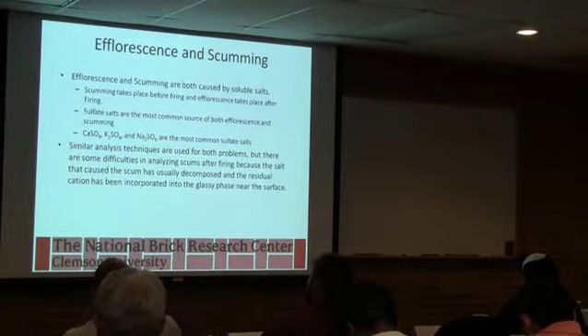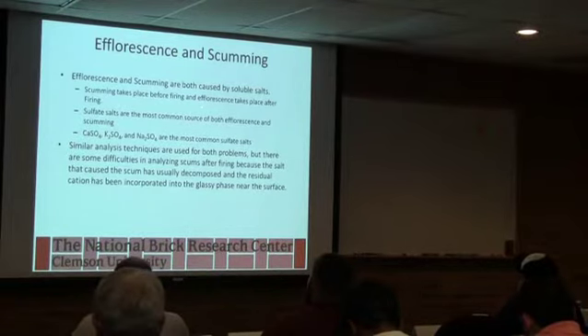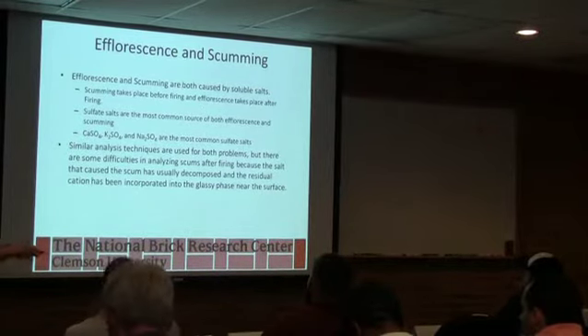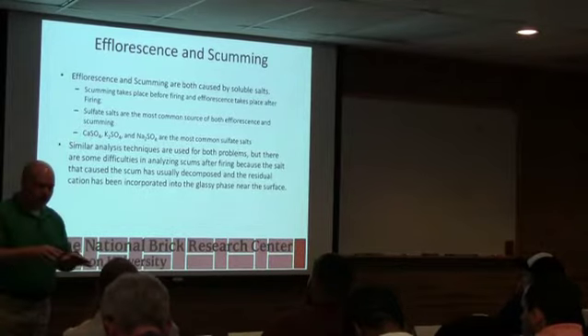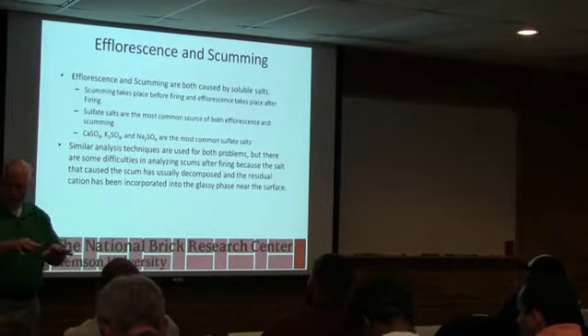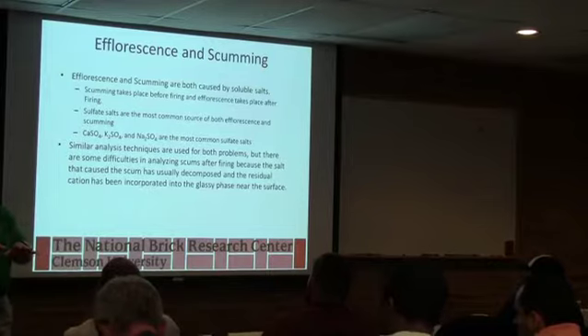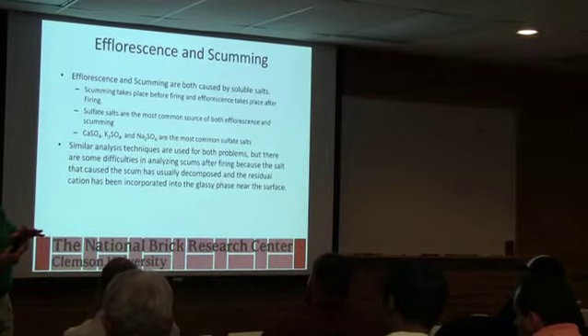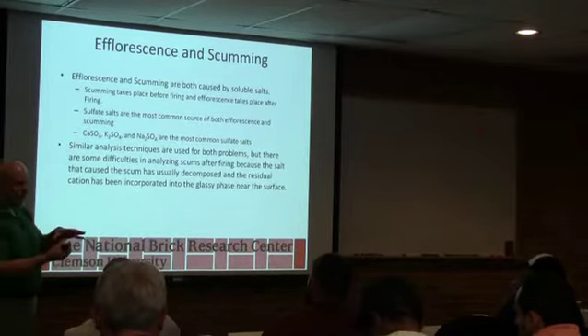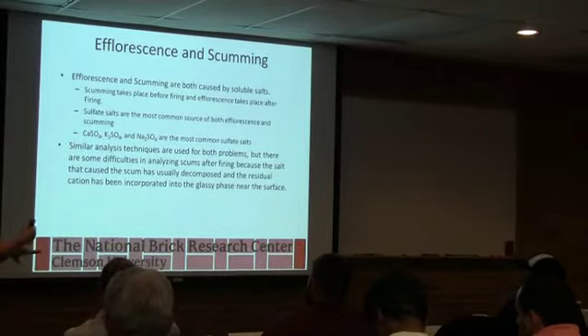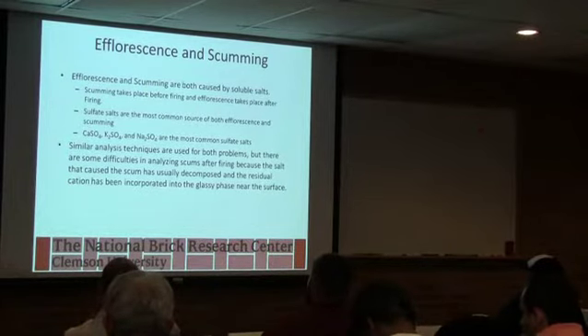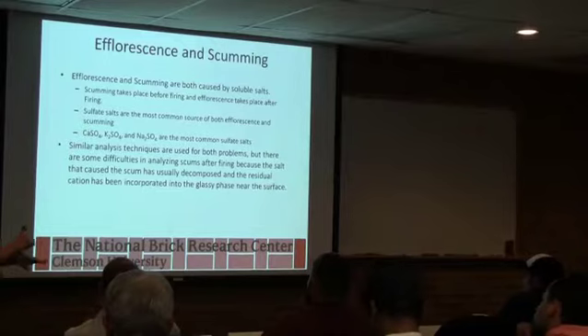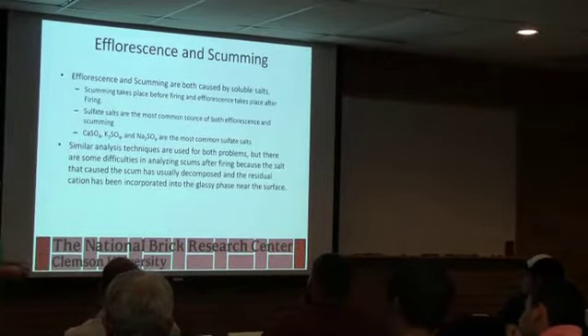Just remember, scumming takes place before firing, typically in the dryer. There's usually a pattern to it. If you're setting on, like the Sealy plant, you used to be able to see where they sat on the trays. You could see where there were holes, and where the air was hitting the brick, and you get salts right in that hole. If you've got brick stacked, wherever air can pass through, typically you'll see the salt deposit. Wherever the brick's covered, you don't see the salt deposit.